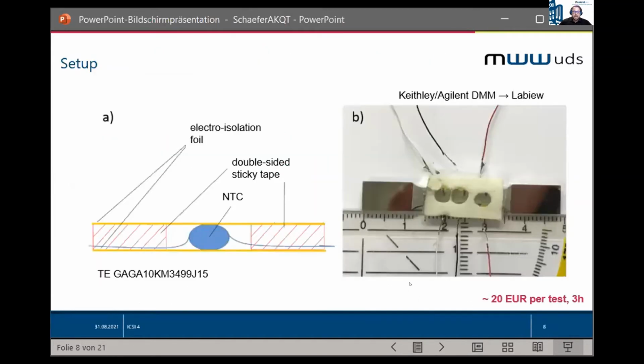So what we do now is we carry out a stepwise load increase test, and we measure the heat generated per load cycle from 3 NTCs. And what we do now is we pack our NTCs in a package of electro-isolation foil and double-sided sticky tape, put 3 sensors together, and use digital multimeters read out with LabVIEW to get the temperature profile of these small samples.